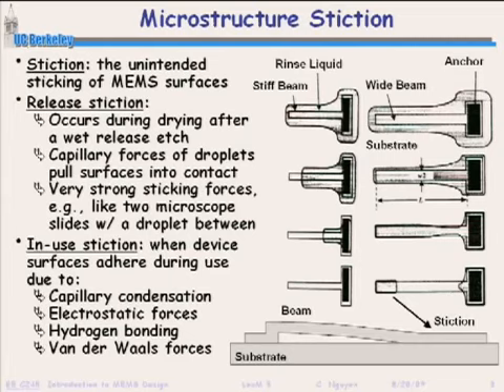But what you find is, after you dry it, the long beams are stuck to the surface. The short beams are not. And so this tells you that there's some kind of force holding these beams down. And I gave you the whole story of how we didn't know about stiction in the beginning. So we kept running the process, thinking we'd done something wrong, but the process was perfectly good. We were wasting our time continuously running the process. What was really happening was the structures were released, but they were stuck to the substrate because of this water-based capillary force that we talked about.